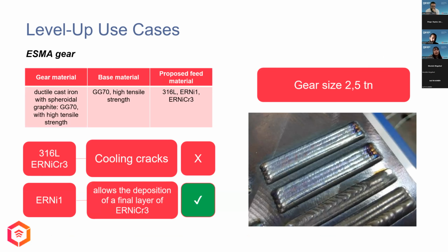This gear is made of GGG70, as commented before, a cast iron with spheroidal graphite. That material is not sold in wire form, so we proposed different materials, a steel and also nickel. Both are hard and cracks appeared during the cooling. The option of the preheating system was studied, but heating the whole gear to a certain temperature is impossible because the part acts like a big sink of thermal input.